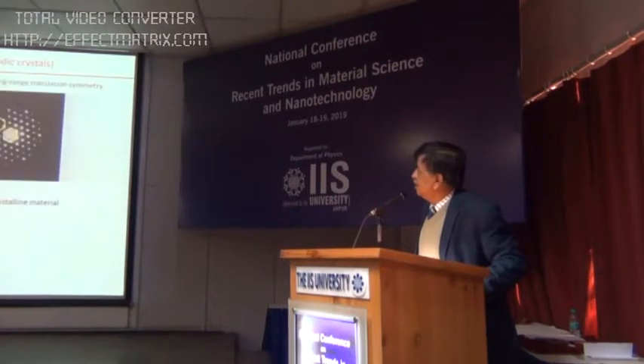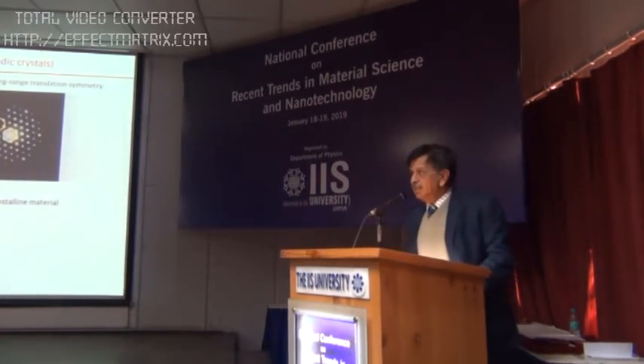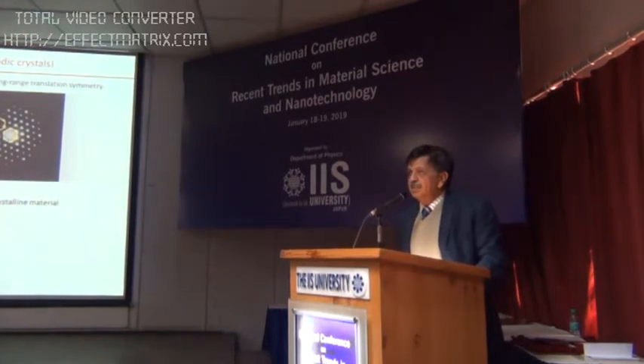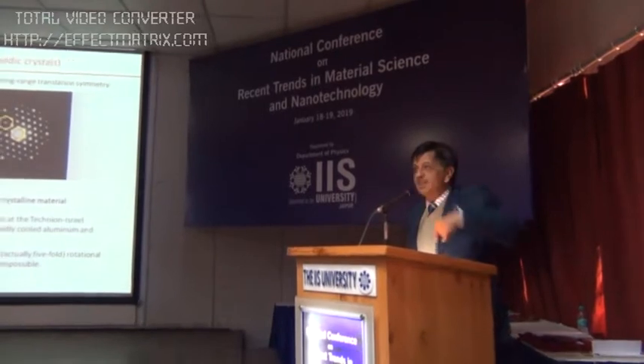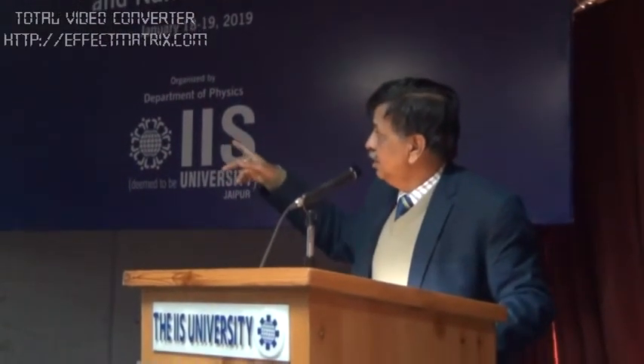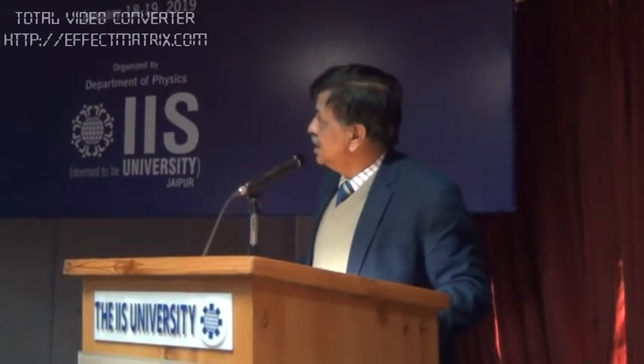Now coming to this high-fold symmetry, you can see that any material has at least two-fold symmetry, because if you rotate it by 180 degrees, the minimum symmetry is that. Then after that, on the right hand side of this picture, you have a kind of 5-fold symmetry. So there are 5 axes about which the system is symmetrical. This is basically a micro electron diffraction pattern, that is, the diffraction pattern from a single crystal, and you find that this 5-fold symmetry exists in this particular system. This comes under the category of quasi-crystals.